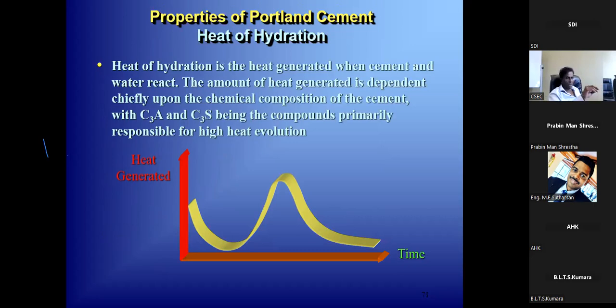Now, again, I will not have time today to talk about what's happening. In specifications, we need to limit that heat generated to about 70 degrees. There are two things we do. The heat generated when concrete is mixed, the temperature increase due to the hydration reaction, we keep to about 70 degrees. The other thing we do is try to keep the difference between the middle of the concrete and the outside surface to less than 20 degrees. We do that, and so those two things need to be satisfied.